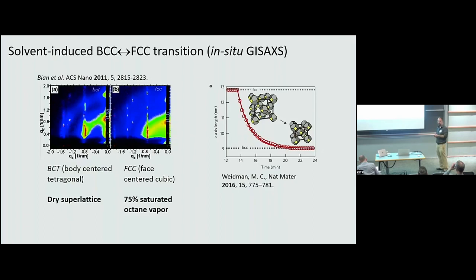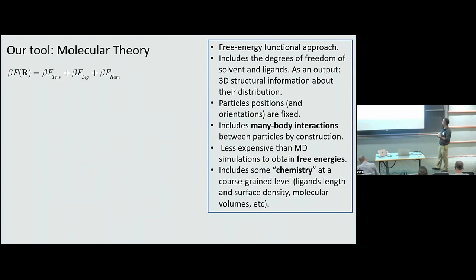So we decided, based on this, to start looking at the problem of how the amount of solvent affects the structure. And so we developed this theory for nanoparticle superlattices, which I will try to give you an idea of. I don't have too much time to explain all the details, but I also want to give you some idea, mostly because this is very different from, let's say, molecular dynamics simulation, so you can get the feeling of what's going on here. The way this is done is you start by writing down a functional for the free energy of the system that you propose.